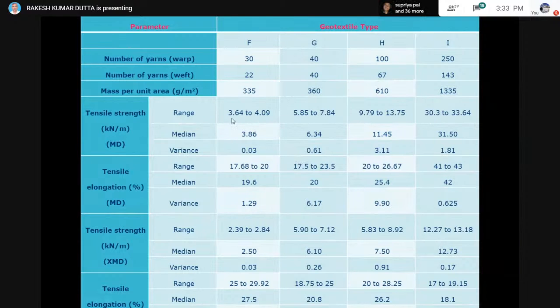So the variation in the tensile strength for the first material was 3.64 to 4.09. For the second material, it was 5.85 to 7.84. For the third material, it was 9.79 to 13.75. And for the fourth, it varied from 30.3 to 33.64. That was the variation. Now, the question is which values to be taken?